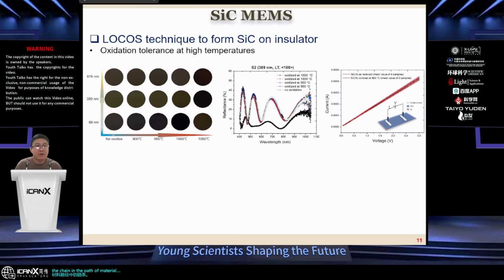So when we tested around 950 degrees C, we saw almost no color change in silicon carbide on the silicon substrate. But above that, we found that silicon carbide starts to oxidize, which also matched really well with the optical profile. The optical profile showed that silicon carbide was relatively stable if we oxidize below 1,000 degrees C. Above 1,000 degrees C, you see a significant drop in the optical reflection.